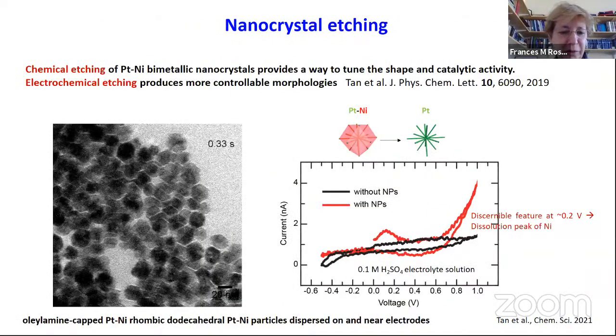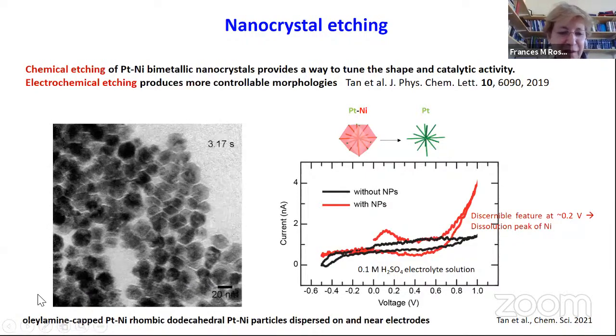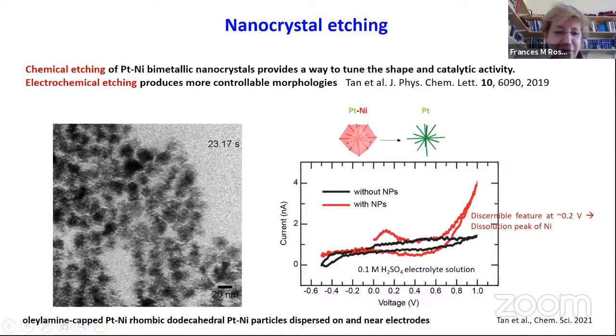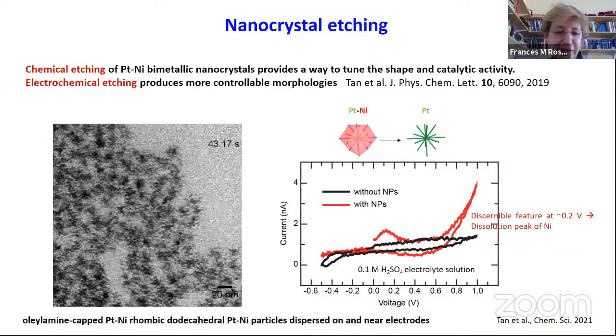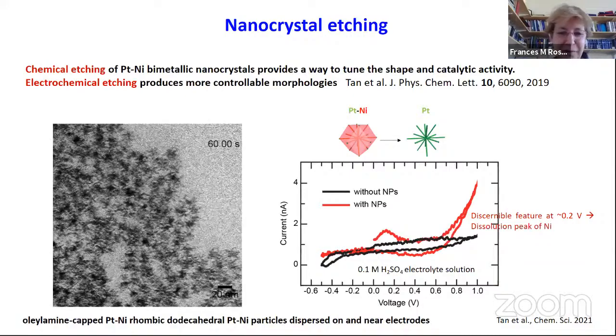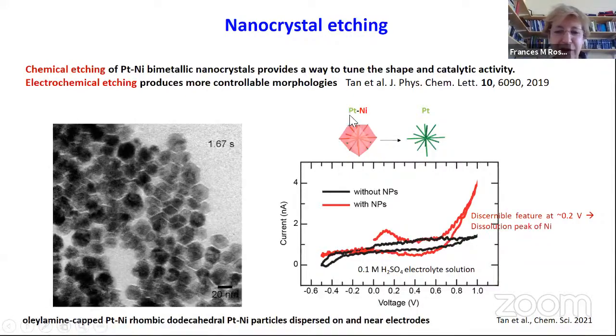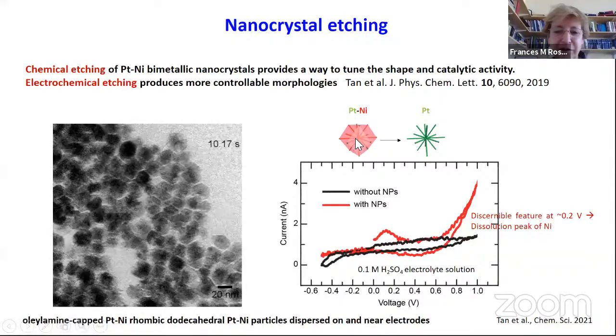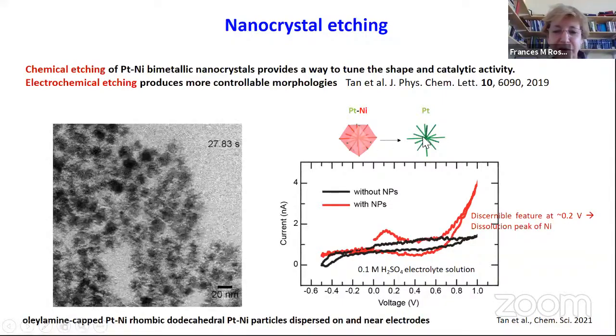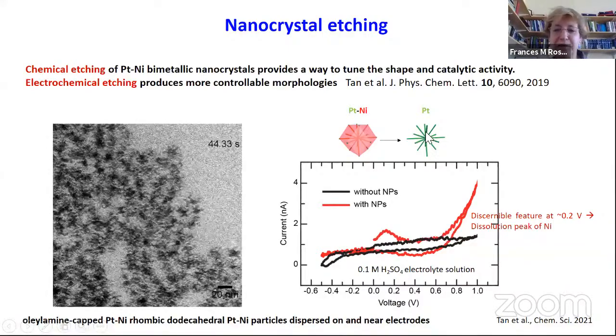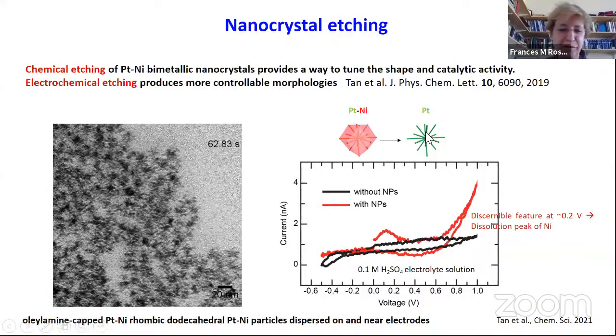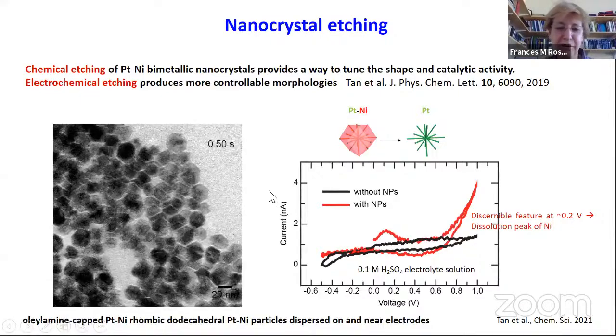Here's a corrosion experiment where we're etching away one component of a bimetallic particle. So in this movie, you can see things that were originally kind of solid polyhedra, and they end up as these little finger-like structures. And what's happening is that the initial structure has platinum deposited as these kinds of lines. And then the nickel fills in the space, and as you etch away the nickel, you end up seeing the platinum structure. So the idea here is to control the surface chemistry by rebalancing the nickel and platinum in these catalyst particles.